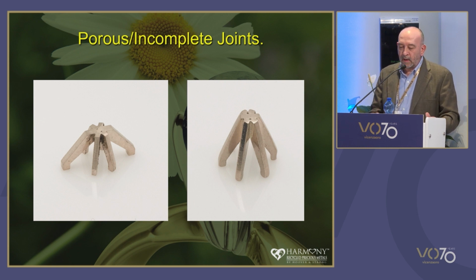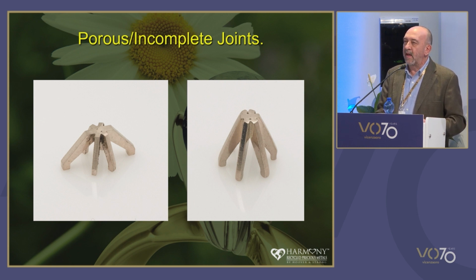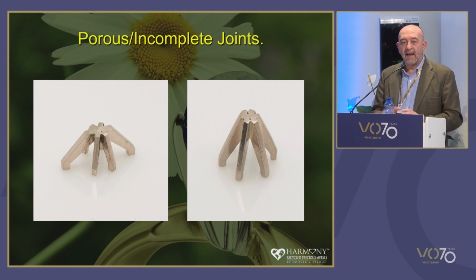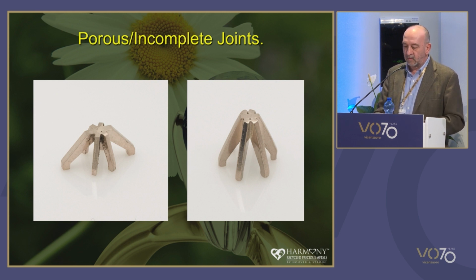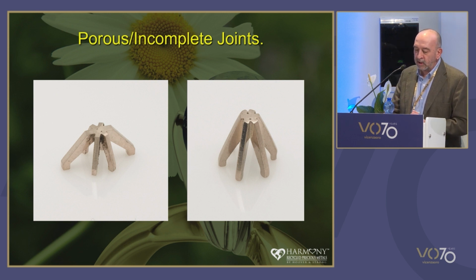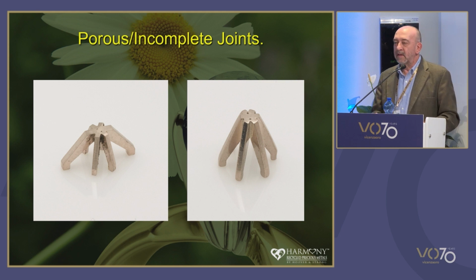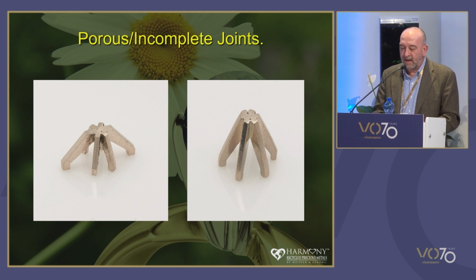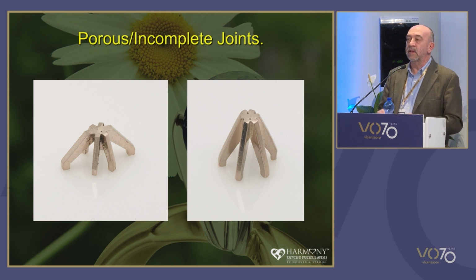So when we examined the process, it wasn't only the joining of the head to the shank that resulted in porosity, it was also when we made the heads themselves. We had porosity, we had voids, as we can see here in these couple of examples. Initially, the solder was blamed, and the investigations all focused into the area of the solder to try and identify this problem and then to try and eliminate it.